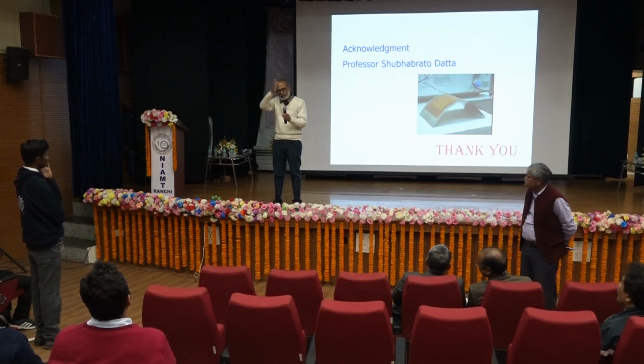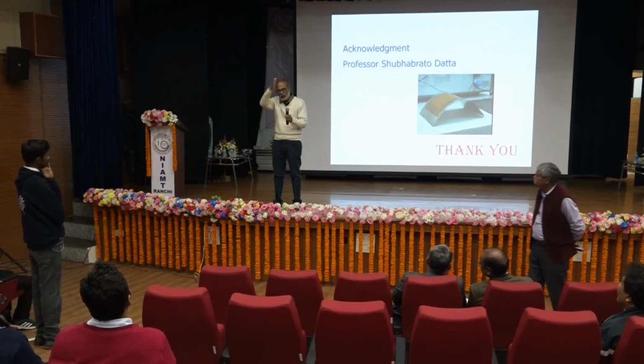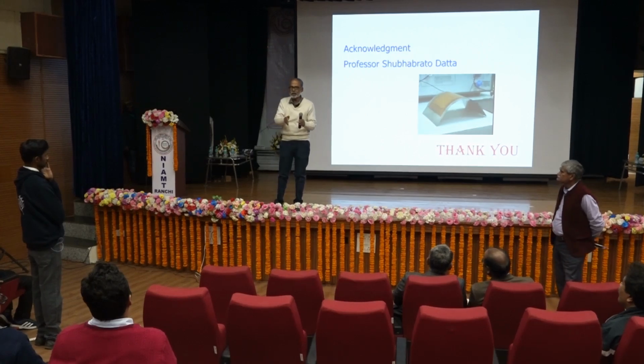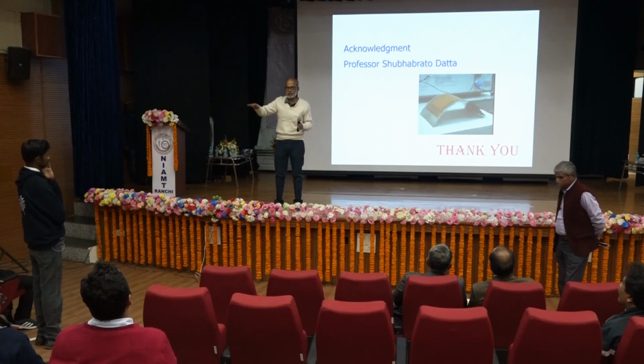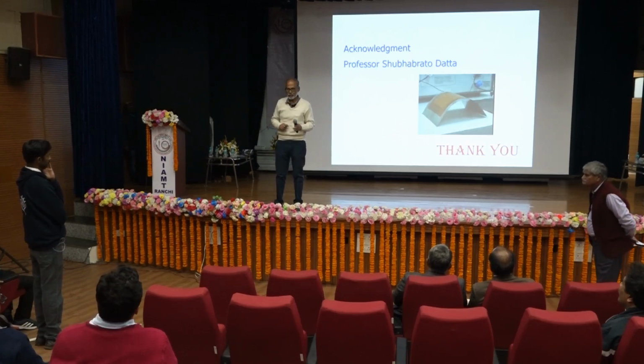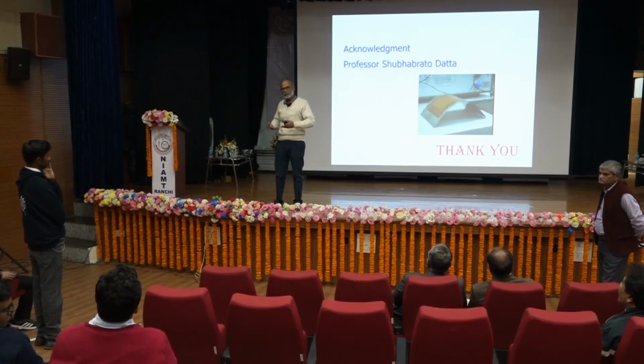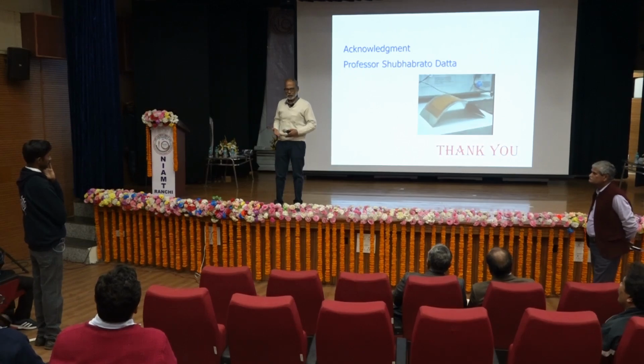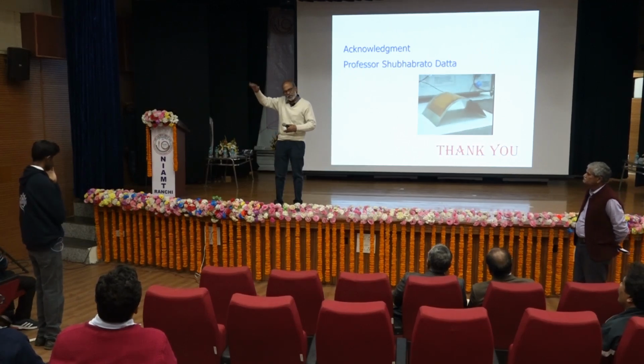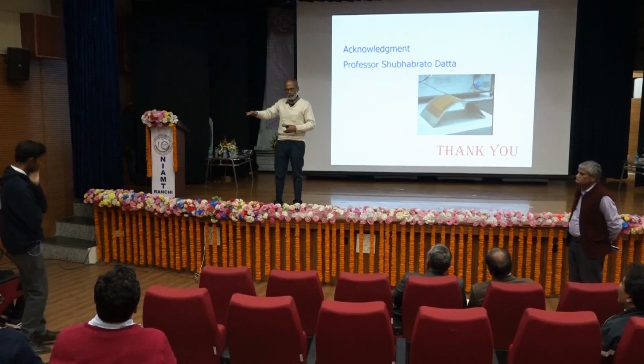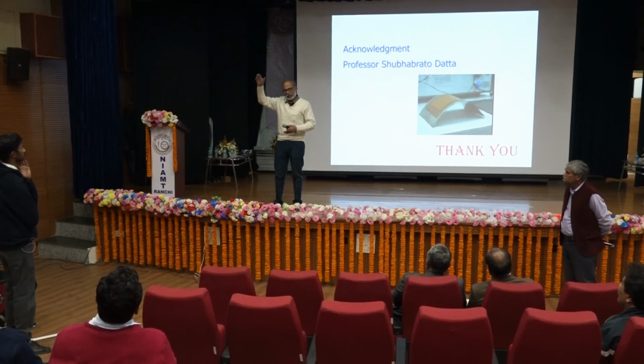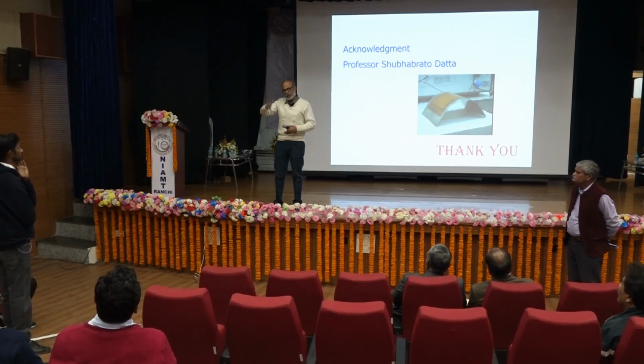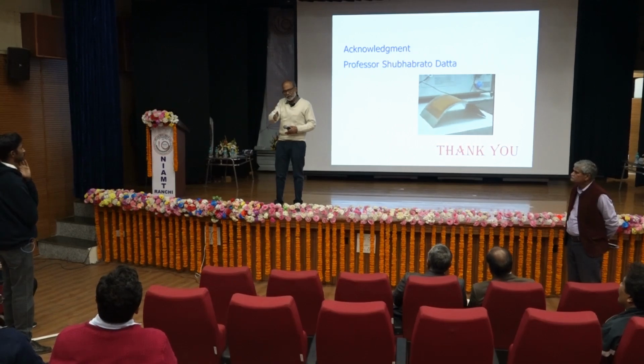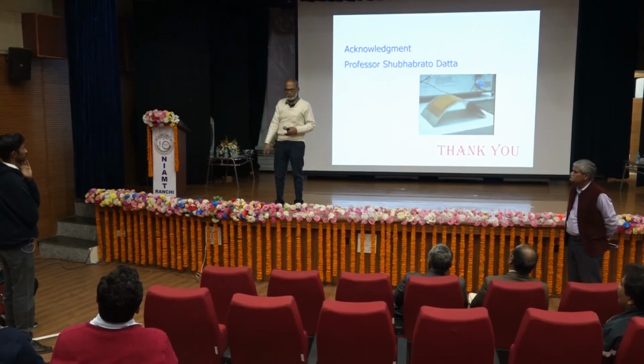And this influences only the boundary in terms of dislocation and twin. When a slip passes through the crystal, it doesn't change the atomic locations. So atomic arrangement, atomic periodicity remain intact. Only you have certain steps at the boundary. And that's how the interface between austenite and martensite can adjust and remain invariant.